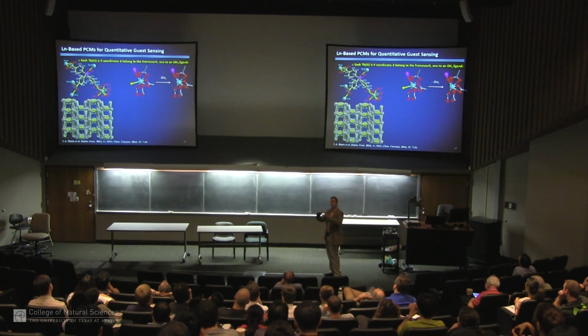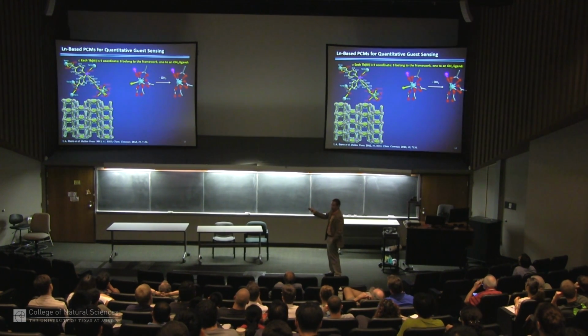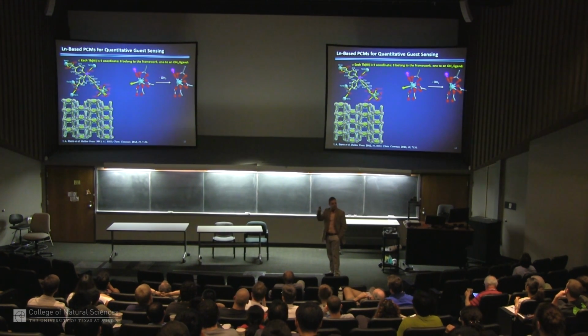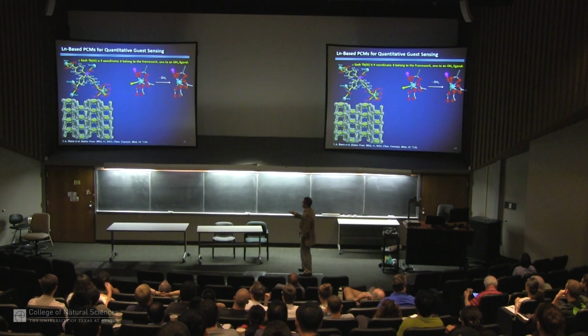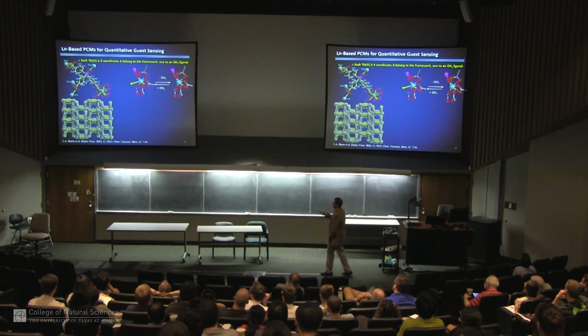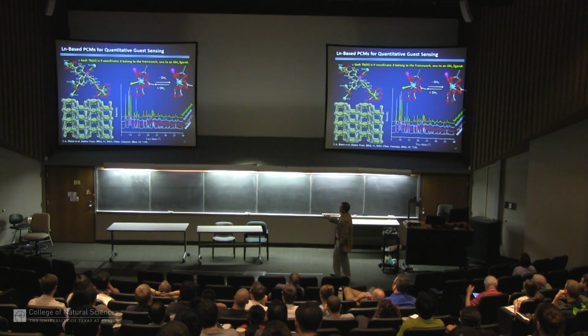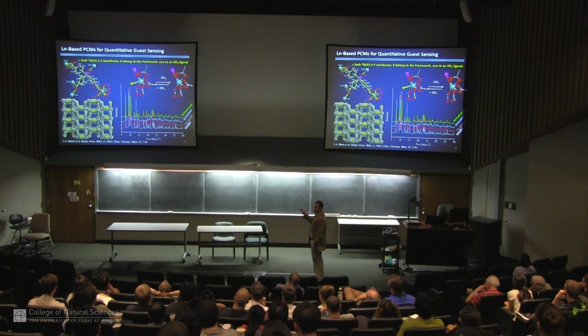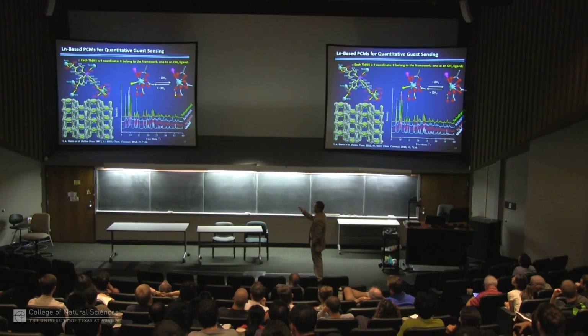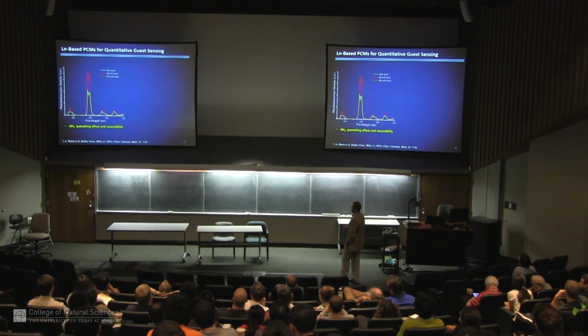Now, if this was a molecule and you removed one ligand, all of the other ligands would move around to take up the spare space. This can't happen in a framework because it's rigid, and so we have this open receptor site that we've generated on every single metal, and it sits inside the pores. It's completely reversible. You can put this back on with steam or vapor, and if we do a measurement which is representative of the bulk, to make sure this is working in the bulk, you can see the crystallinity of the material is completely intact in either state. Nothing's happening apart from the single water being removed.